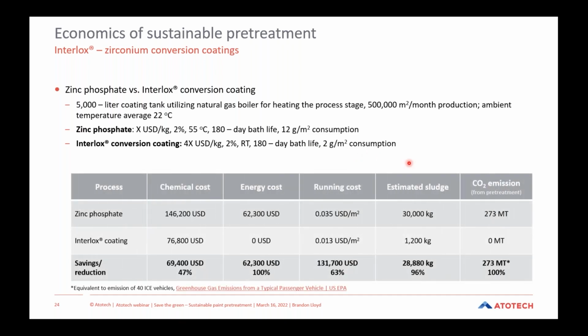So now looking at all the associated costs that come along with considering a conversion from a zinc phosphate to Interlox. Here we can see in the first column the chemical cost. We're able to reduce that by almost 70,000 US dollars per year, which is almost 50%, right at 47%. Looking at the energy cost, we're able to completely eliminate all energy demands that are associated with the conversion coating step itself, which in total is equivalent to about 62,000 US dollars.